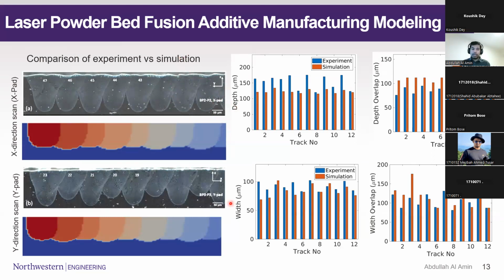In addition to the depth and width measurements, there were also some measurements involving the depth overlap, meaning from the top surface and at the bottom, when those two melt pool geometries overlap, what is their depth?